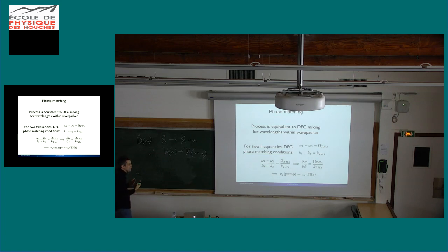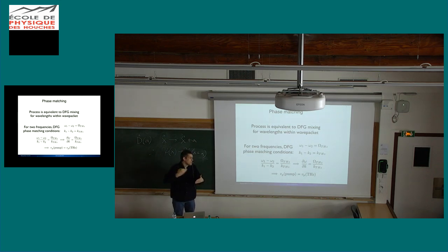And that kind of makes sense, because if that weren't true and you had a long crystal, that would mean that the terahertz that you generate from the front part of the crystal would start propagating into the rest of the crystal. If it would have a phase velocity that's not matched with the group velocity, then at the end of the crystal, the newly generated terahertz radiation, because the terahertz radiation is generated by the envelope of the pulse, and the time dependence, the propagation of the envelope, is governed by the group velocity. And so at the end of the crystal, if you didn't have this matching, you would have a mismatch between the newly generated terahertz and the terahertz that was generated at the front of the crystal. And so you get destructive interference. So you lose your phase match.